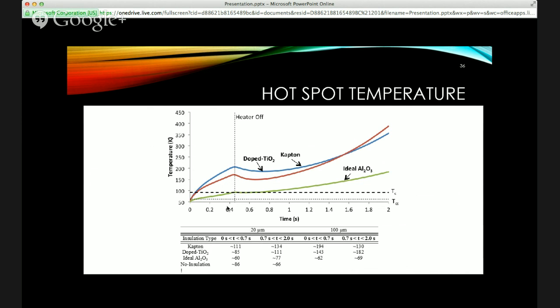What you'll see is that the higher your thermal conductivity, the lower your peak temperature, even after time has passed. All of these simulations were conducted for 2 seconds. But 2 seconds does not mean 2 seconds real time. 2 seconds in the time of these models means 13 hours in real time.